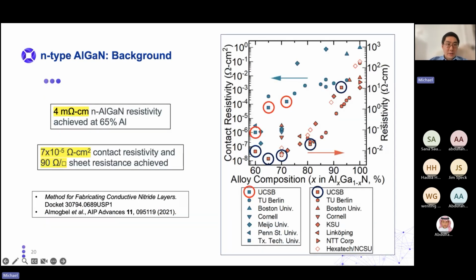So with this work, we were able to achieve easily and consistently 4 milliohm centimeters of resistivity at 65% aluminum, which is among some of the best resistivity in the world, and 7 times 10 to the minus 5 ohm centimeter squared contact resistivity, which is also some of the best in the world, and a sheet resistance of 90 ohm per square, which is extremely good for this high aluminum in AlGaN.